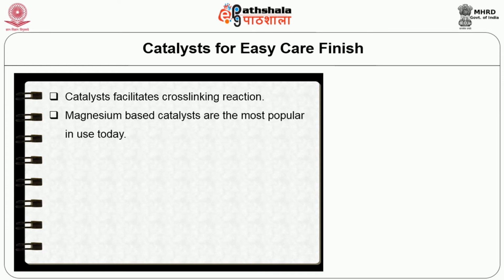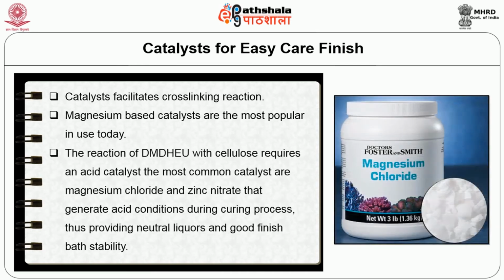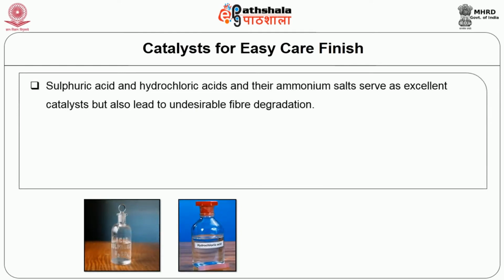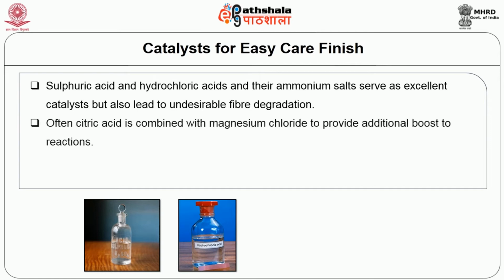Magnesium-based catalysts are the most popular in use today. The reaction of DMDHEU with cellulose requires an acid catalyst. The most common catalysts are magnesium chloride and zinc nitrate that generate acid conditions during the curing process, thus providing neutral liquors and good finish bath stability. Sulfuric acid and hydrochloric acid and their ammonium salts serve as excellent catalysts but also lead to undesirable fiber degradation.